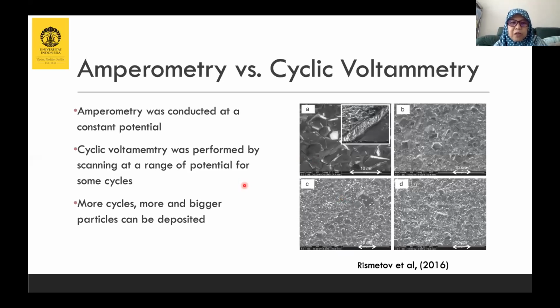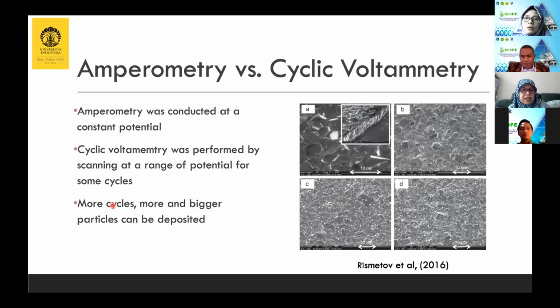With electrochemical deposition, we can use two kinds of techniques, amperometry or cyclic voltammetry. What's the difference? Amperometry uses a constant potential, while cyclic voltammetry is performed by scanning a range of potential for some cycles. With more cycles, generally more particles will be deposited. Particles are deposited during reduction, and then removed during the oxidation step, but after some cycles, some particles remain deposited. Here is an example of the surface of diamond with deposition by the cyclic voltammetry method.